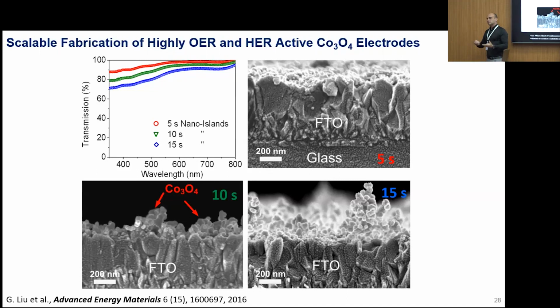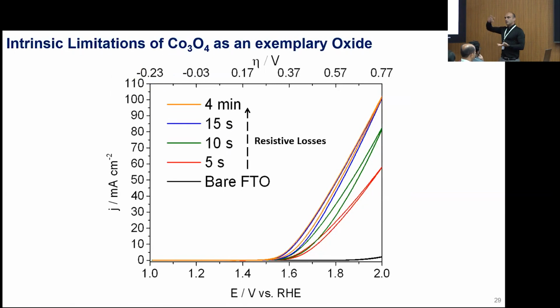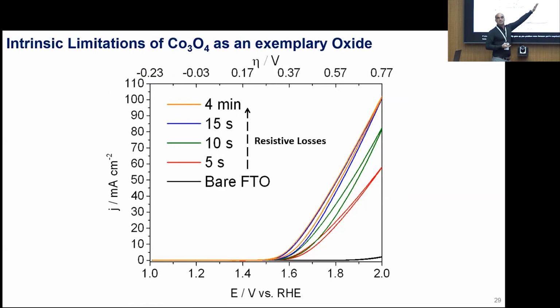Now, what you expect is, if you increase the time, your activity goes up. You produce more because you have more surface area. However, this is true only up to a certain time. When your layer gets too thick, as I will show you here, then you have only dead catalysts. You're wasting your material. And this is because oxides have a major issue. They are not very good conductors.